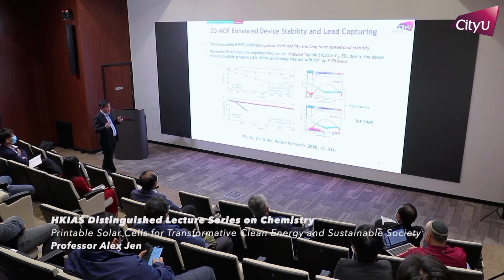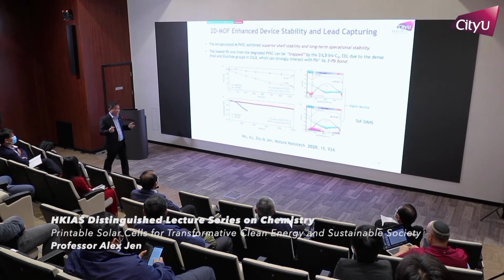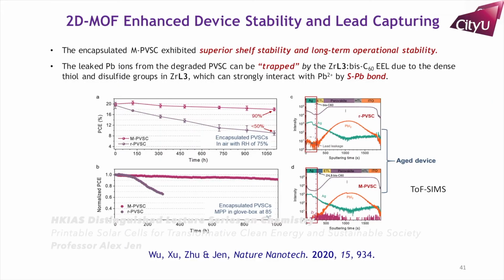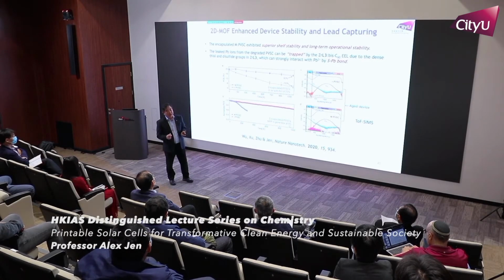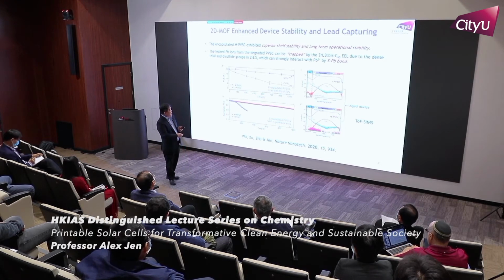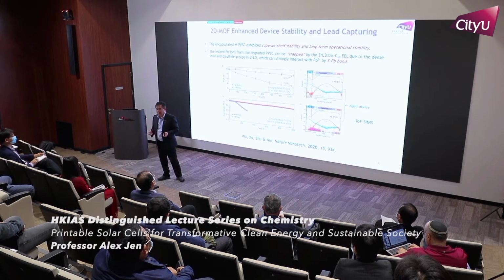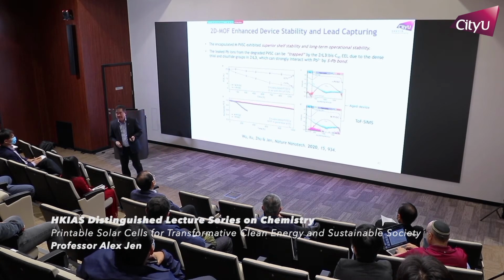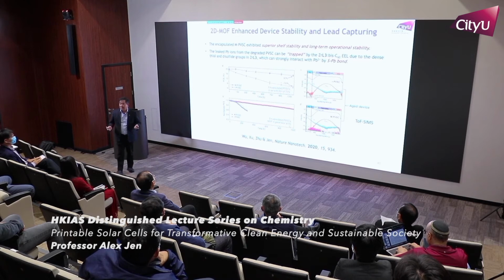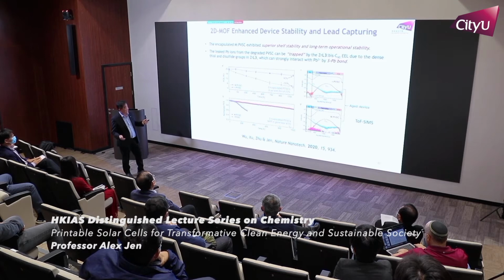And most importantly, in order for things to be commercial, you always have to fulfill the so-called Telcordia 85-85 test. This is 85 degrees C, 85% humidity, and you heat it under sunlight in the operating condition for 1,000 hours. This is a so-called accelerated testing. It is a very stringent test. It's not just a lab demo. So you can still have very nice stability out of this.